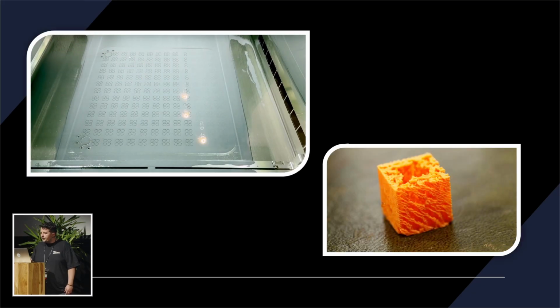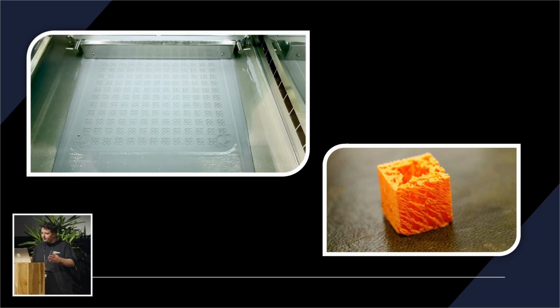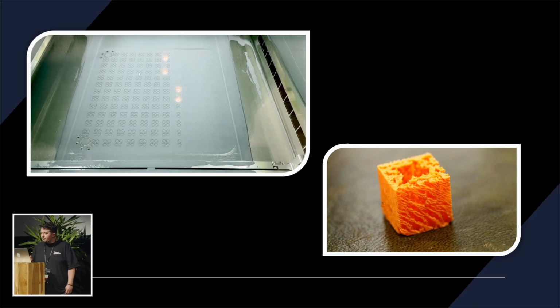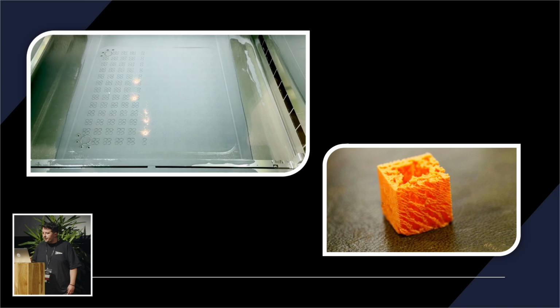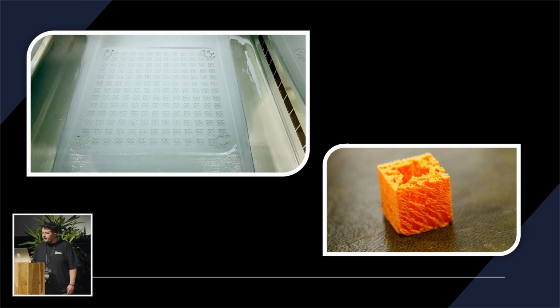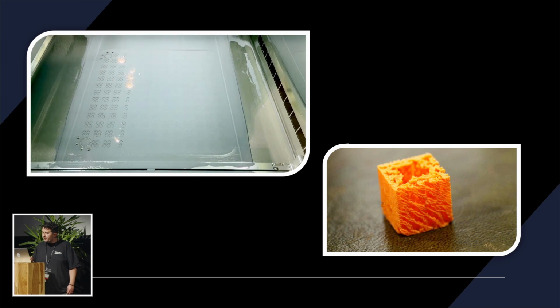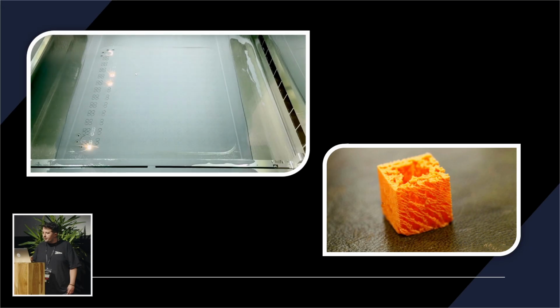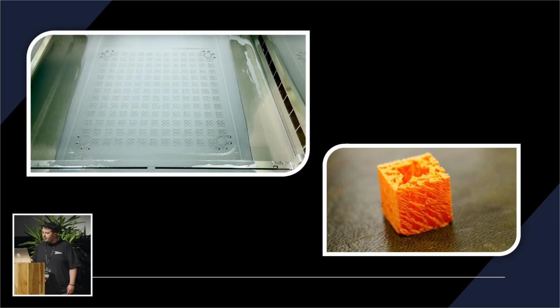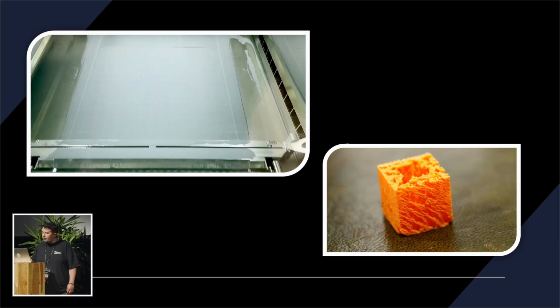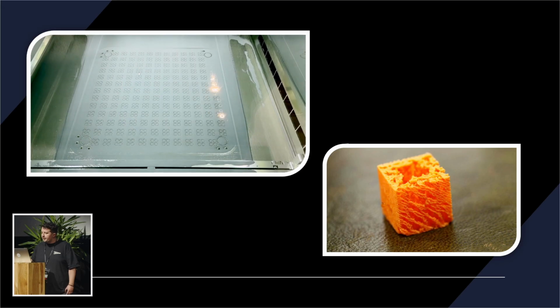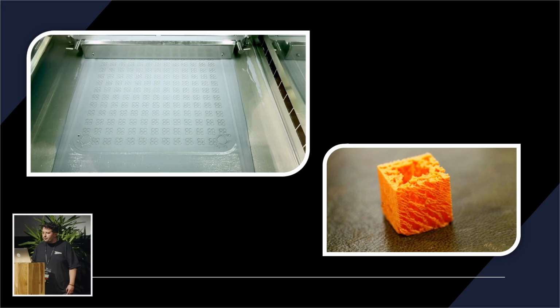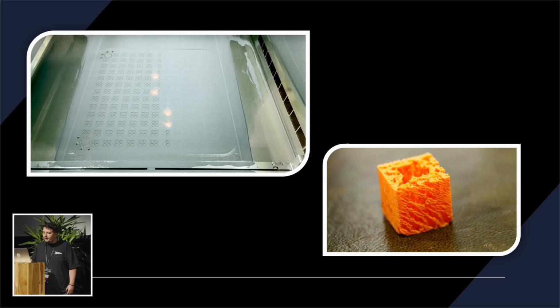So at Alloyed, we struggle with the dosing and spreading of the metal powder, making sure there's enough material each layer and it isn't underdosing. If you watch this video, you can see a small amount of fine metal powder is released, and then the recoater comes across and wipes a thin layer across the build plate. After this, the laser fires and pretty much welds a layer to the metal build plate. Then the build moves down in the Z-axis by 30 microns, and the process is repeated over and over, building up the parts layer by layer.